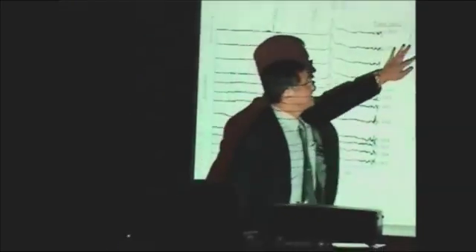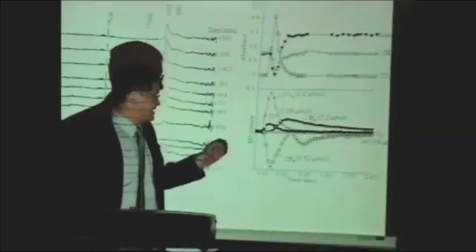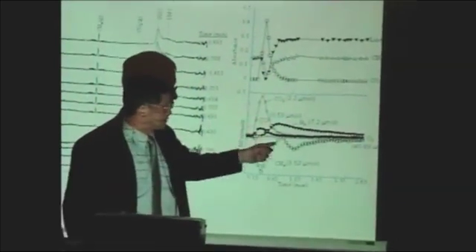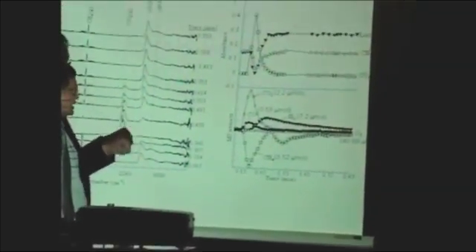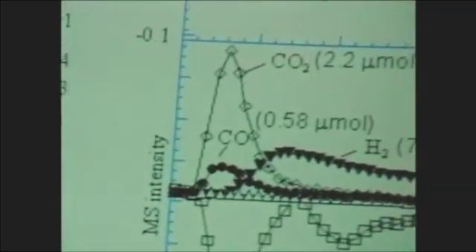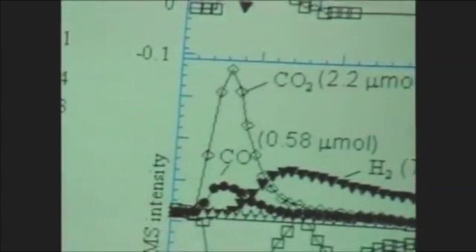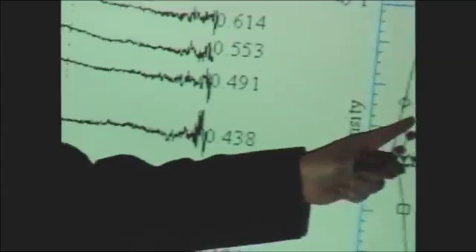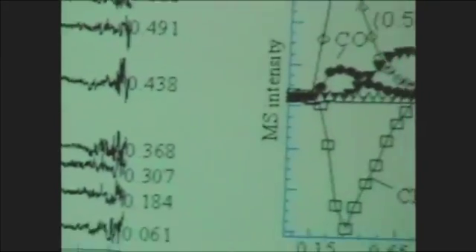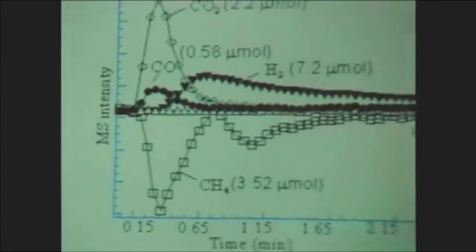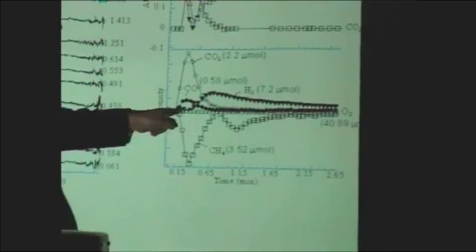And let's take a look at the mass spec result here. This is the evolution of the product coming out from the reactor. Once the oxygen is coming in, immediately we see the formation of CO2. Following the CO2 formation, surprisingly, we see the formation of CO instead of hydrogen. So in the partial oxidation reaction here, what we found is that CO is forming first, and hydrogen is forming later.